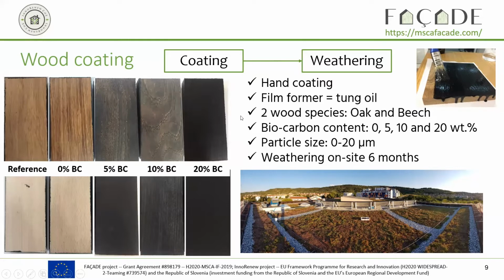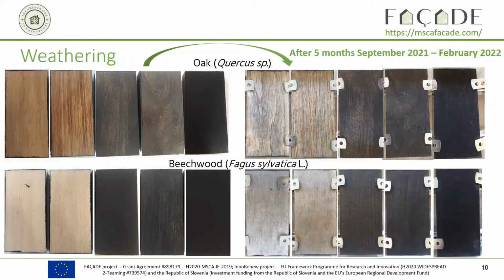And then we studied the weathering effect by leaving these samples on the roof of our new building. So you can see the little white spots in the middle of the picture. These are the samples. And on the picture, it looks like very nice weather, but they were left for 5 months during the winter. And this is what the samples looked like after 5 months, so beginning of February, on the right. Now, how to quantify the changes of this sample and of the coating?